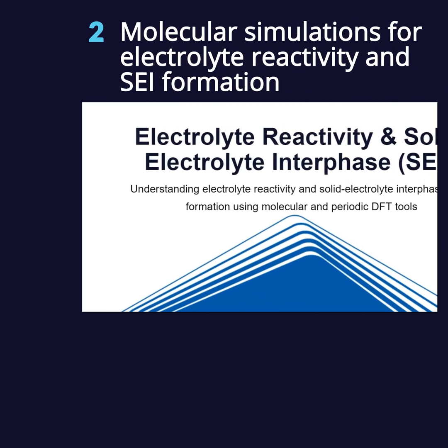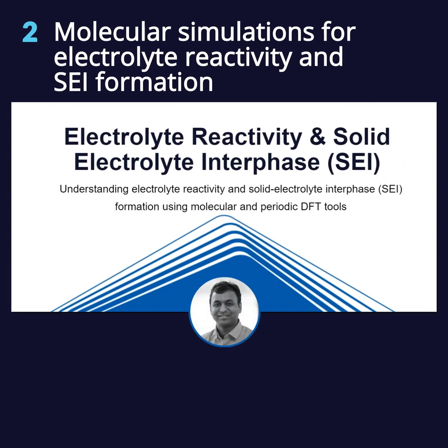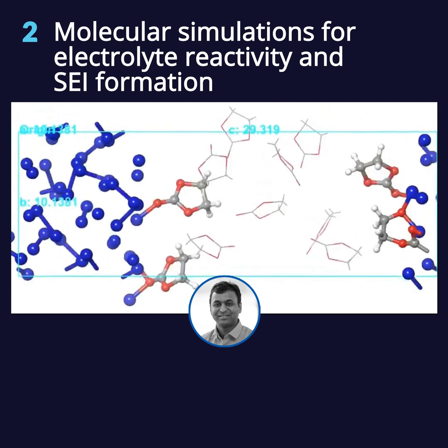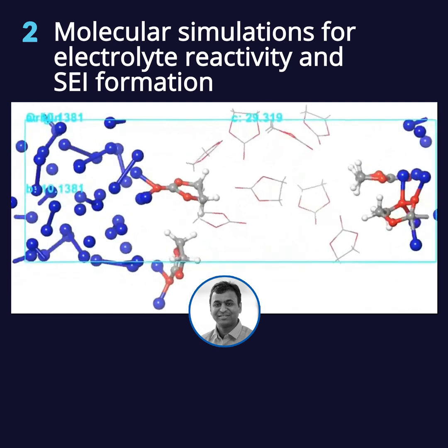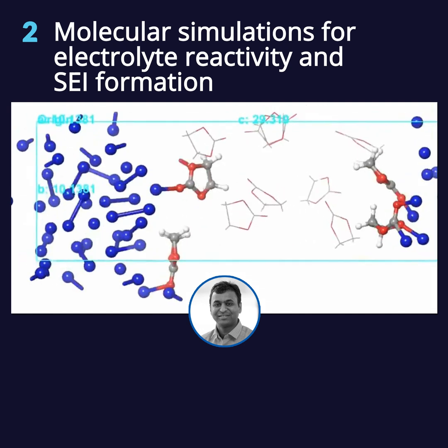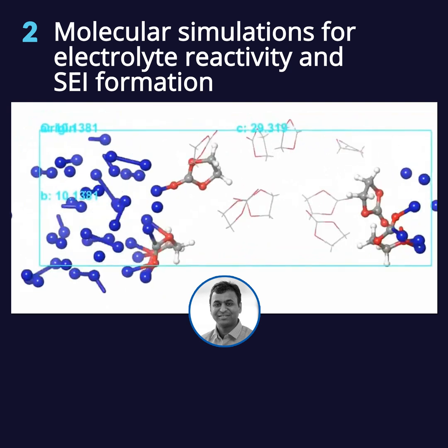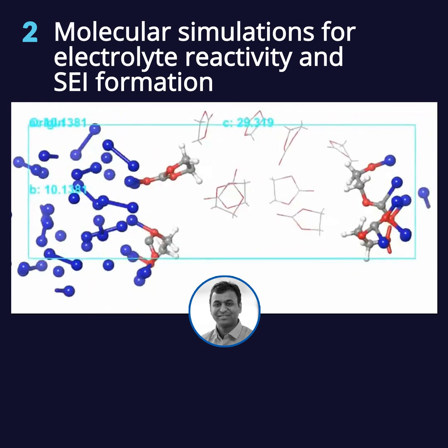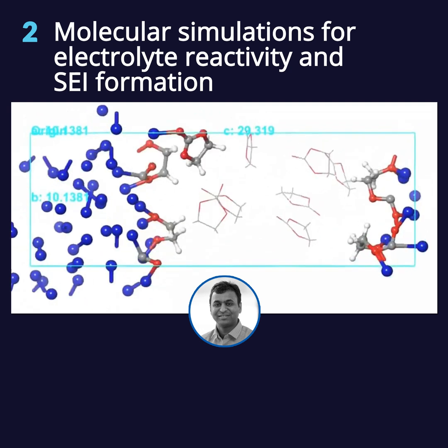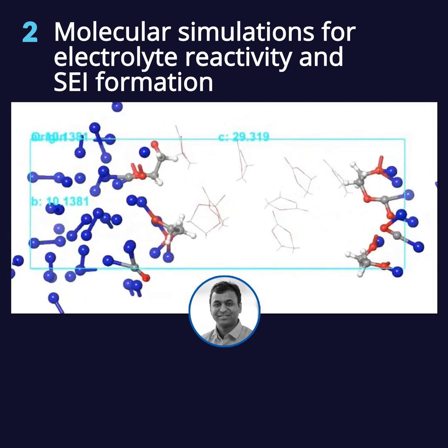surface. So to begin with, I'm going to demonstrate how we use atomistic modeling tools to dive deeper into electrolyte reactivity and understand solid electrolyte interface formation in lithium-ion batteries. As you can see in this MD trajectory, EC molecules near the two lithium metal surfaces react spontaneously to decompose via carbon-oxygen bond dissociation reaction, resulting in a formation of multiple CO gas molecules and other oxygenated fragments which remain adsorbed on the surface of this lithium metal.